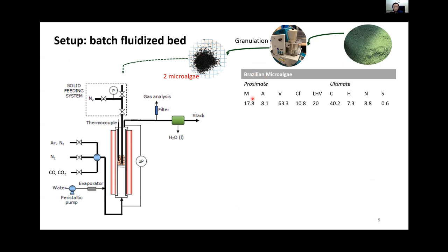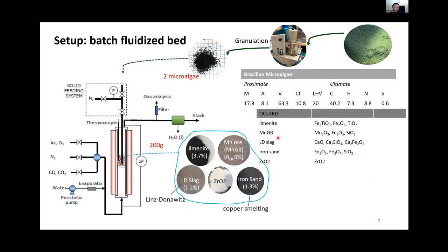And we can see in this table, the algae has 63% volatiles and 11% fixed carbon. And we use 2 grams of microalgae for every test. We use ilmenite, manganese ore, which is called MNGB, and LD slag, iron sand as the oxygen carrier candidates. The ilmenite is an iron titanium ore, and the manganese ore is a manganese iron ore, whereas the LD slag and iron sand are industry byproducts. And zirconia is also used as inert, either mixing with the oxygen carriers or just as bed for blank tests.